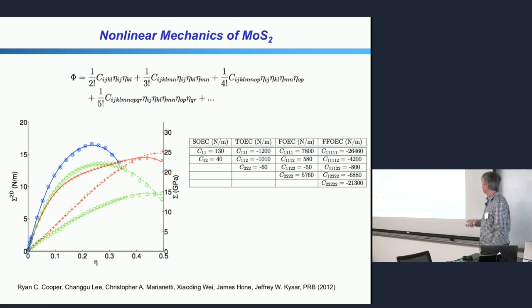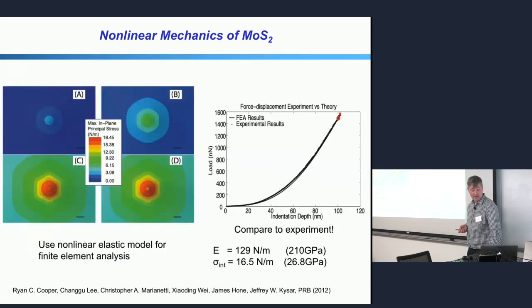Again, you can get these 14 elastic constants. The symmetry is very, very similar. And once again, you can do these experiments, and again, you can look at the load versus indentation depth, and not only do you get a good fit to the load displacement curve, but actually you get a good agreement between theory and experiment for the maximum strength, the breaking load as well. So this is very nice.